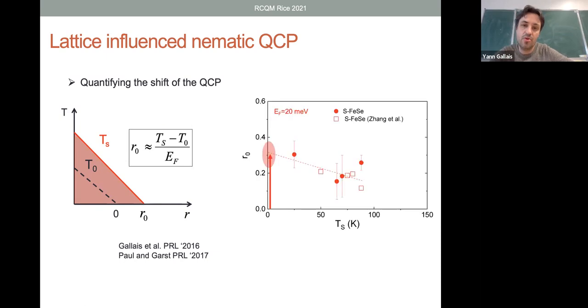So this is the result. This is this coefficient as a function of T_S, and the shift here is indicated by the arrow. If there was no coupling to the lattice, so if the nemato-elastic coupling constant was 0, the QCP would be at the origin of this graph. When T_S would go to 0, R_0 would be 0. And here you see that there is a relatively significant shift, with a value of R_0 of about 0.3.